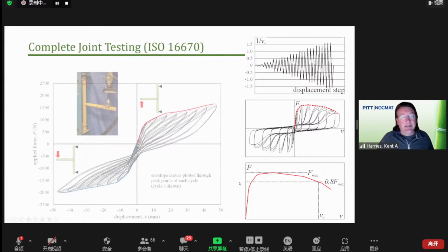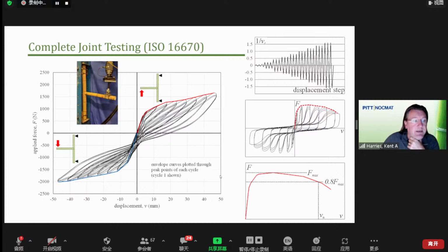And so if we take a look at the data from our particular test, we have applied force vertically, displacement horizontally. Again, we're testing in reverse cyclic behavior. So as the actuator pulls up, we're on the positive side up here in the upper right quadrant. And as the actuator pushes down, on the negative side. And for those of you familiar with this kind of testing, we have a really nice pinched hysteresis behavior. 3 cycles at each displacement, with the cycles decaying a little bit.